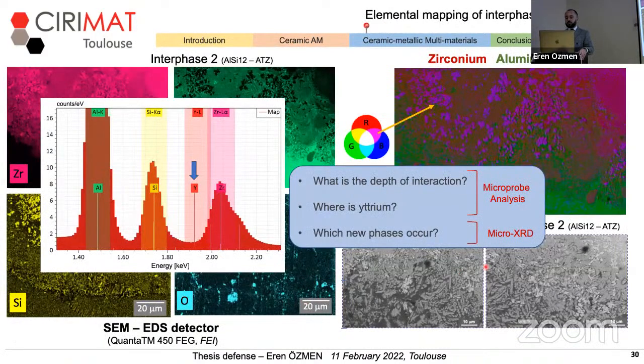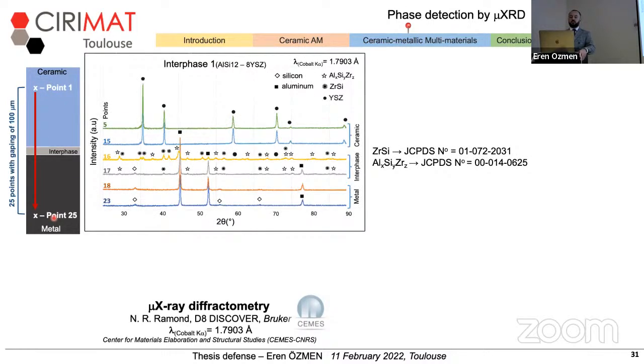So to answer the second part of the question, what are the possible phases occurring in this interface, I performed micro XRD analysis as well. To do that, I followed a path full of measurement points, 25 points with a gap of 100 micron, starting from the ceramic part, going to metal, passing through the interface. When I check the XRD pattern of all these points, I see that 2 points correspond with interface 1. When I check the possible phases by comparing the peaks with the XRD database, I see that an intermetallic phase between zirconium and silicon, and also a ternary phase among aluminum, silicon, and zirconium, appears in the structure.